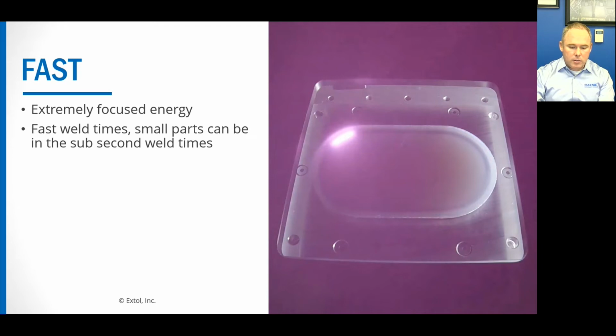Fast, we talked about. You saw this image earlier. We've got other videos that sort of show this, but you can have, like I said, 1 second. Actually, I think we ended up doing like 1.5 seconds, a really small part. For larger parts, you might get up into the 10-second range. We usually size the wattage of the laser appropriately for the speed and cycle time that you need.